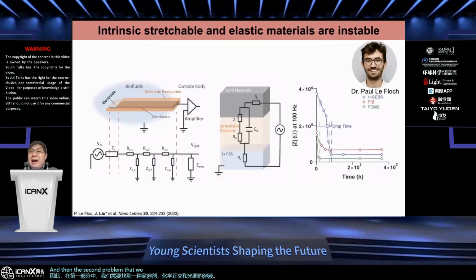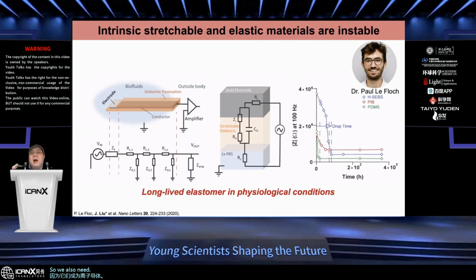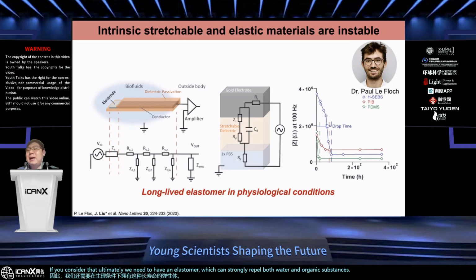And then the second problem that we found is that the ions in the solution can also easily penetrate those dielectric elastomers. Because they are cross-linked liquid at room temperature, and our biofluid is like 37-degree warm and salty water. So the ions easily penetrate into the elastomer, and over time they lose the capability to encapsulate the electronics because they become an ion conductor. But we also need to have this long-lived elastomer in the physiological condition. So ultimately we need an elastomer which can strongly repel water, organic solvent, and ions.